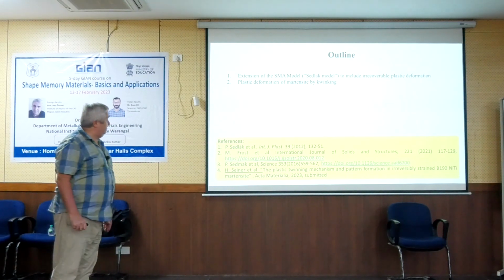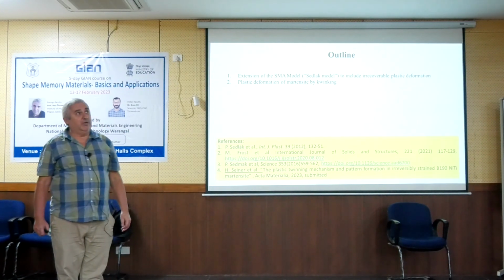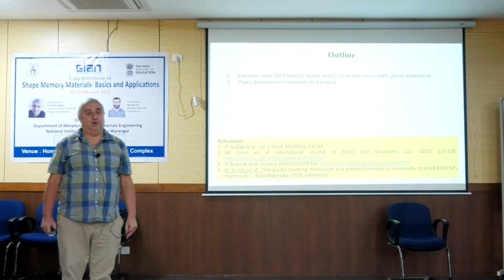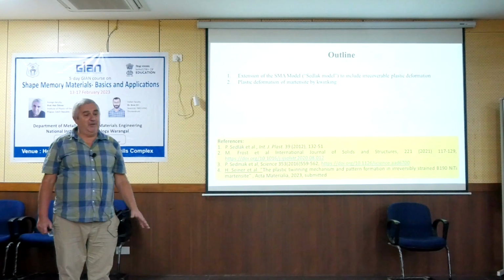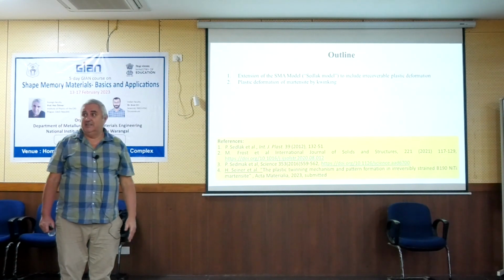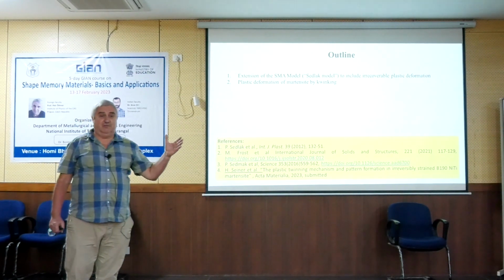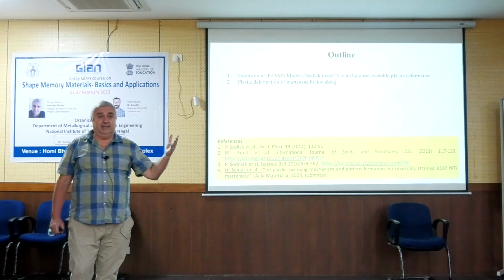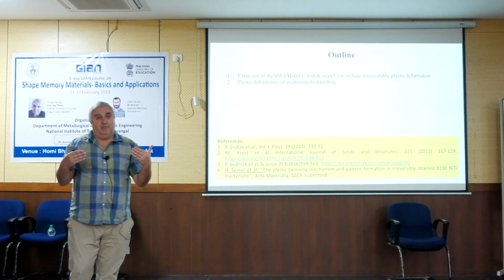For the last maybe 4 years, during the COVID, we couldn't go much to the conferences. I have been working a lot on research focused on understanding the plastic deformation of martensite. Why? Because we found in TEM analysis this kind of deformation bands, and we realized that even the plastic deformation of martensite is due to sort of twinning.